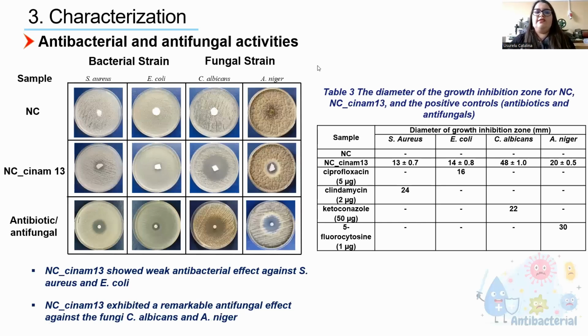The sponge containing nanocellulose and the highest amount of cinnamaldehyde was also tested for its antibacterial and antifungal activities against Staphylococcus aureus, Escherichia coli, Candida albicans, and Aspergillus niger. We can see that the sponges based on nanocellulose and cinnamaldehyde presented only a weak antibacterial effect, both against S. aureus and E. coli, which was manifested only at the contact zone between the cellulose material and the culture media. But the same sponge manifested a remarkable antifungal effect against both fungi, Candida albicans and A. niger, which was manifested by the appearance of a growth inhibition zone with a high diameter.